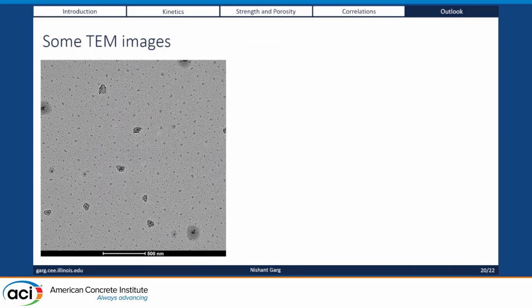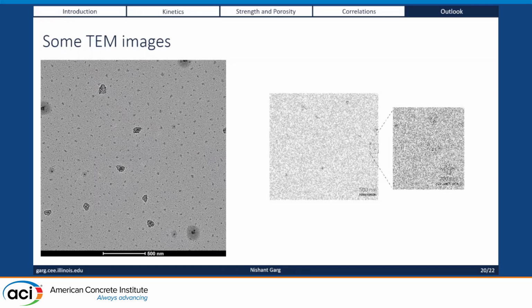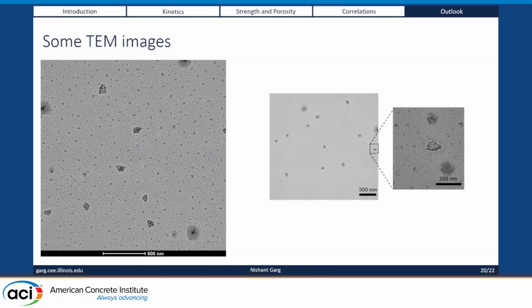If we look at how these seeds look under the TEM, you see these 50 to 100 nanometer sized particles, which are uniformly distributed in the PCE network, and I think this is what does the job. And if you look at the C-S-H individual particles, the images match pretty well what has been reported in the literature for synthetic C-S-H. If you do an X-ray diffraction on the dried version, you also get typical C-S-H peaks. So from that point of view, the purity and the dispersion is done nicely in this product.